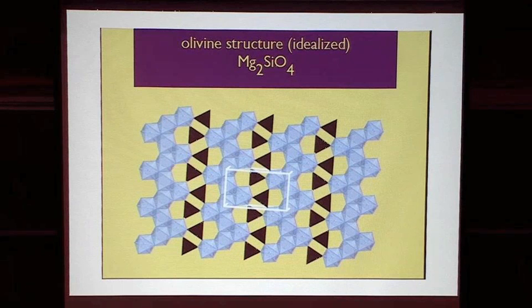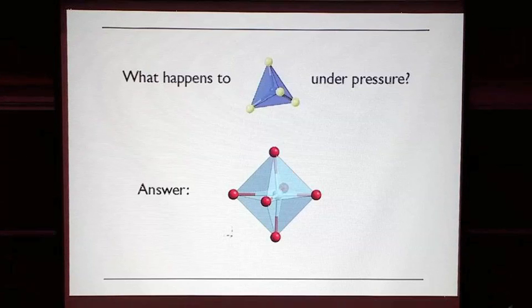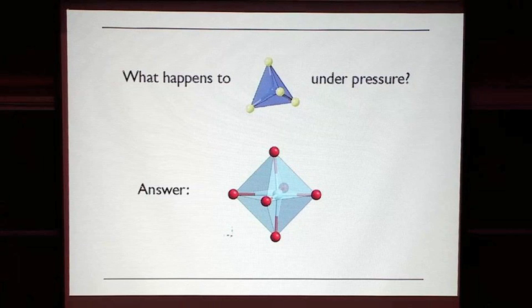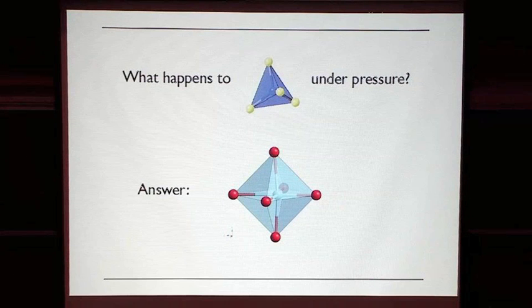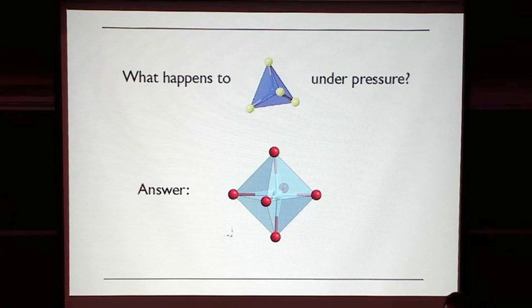Okay. So this actually is really all I'm going to say about the influence of pressure on this, but these cation-anion radius ratios shouldn't be taken, out of Shannon and Prewitt, as the numbers that apply everywhere, because with pressure the bond lengths change, and therefore really the effective cation-anion radius ratio changes. And so with pressure, one begins to get higher coordination and therefore changes in the stability of different arrangements and the stability of different minerals. And I'm pretty sure that G is going to talk about that in a lot more detail, so I will just leave it at that.